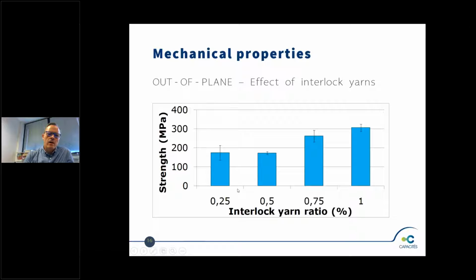And coming back to the interlock yarn ratio, 0.25 up to 1%, then the strength in megapascal can go from a bit below 200 megapascal up to more than 300. It means that we were expecting in the in-plane test a strength which was around 350 megapascal, and by curving the specimen, because we have these interlock yarns, we